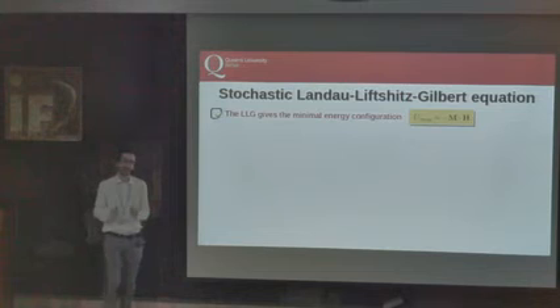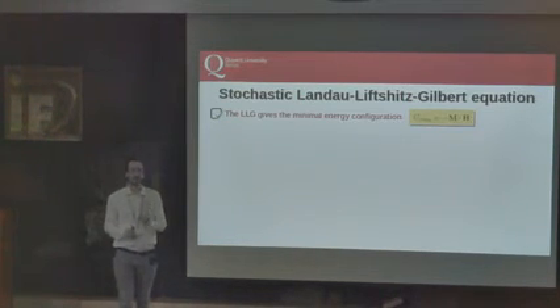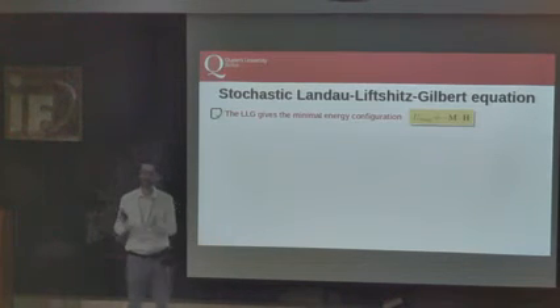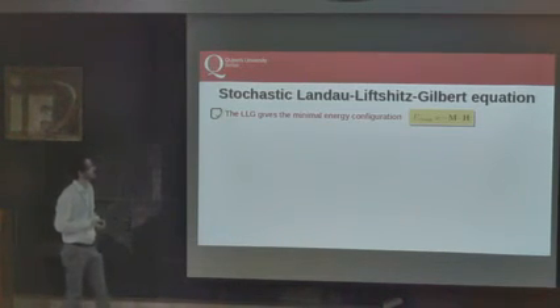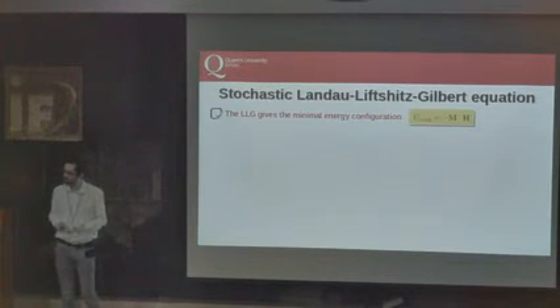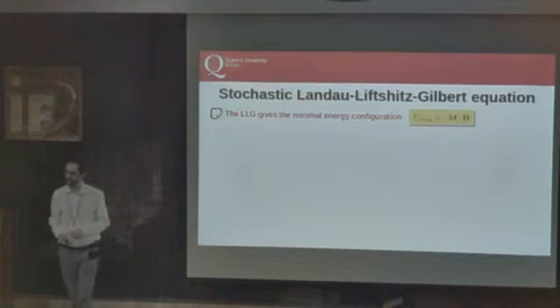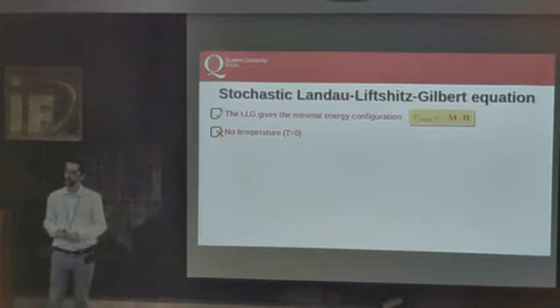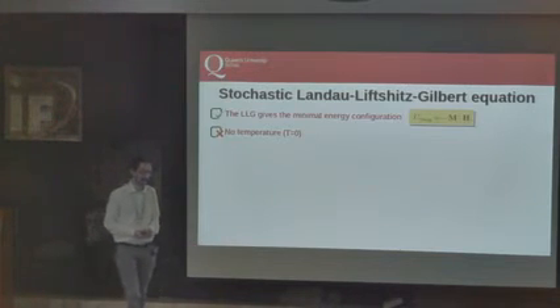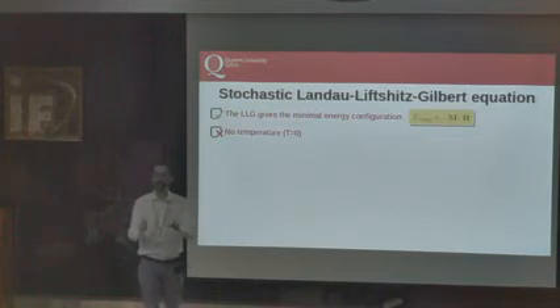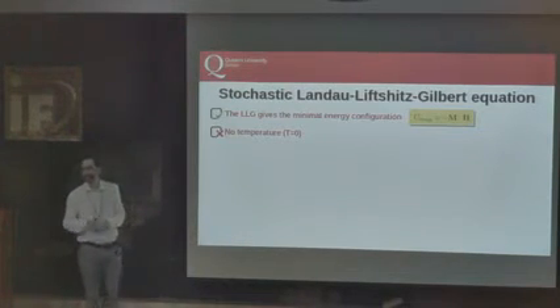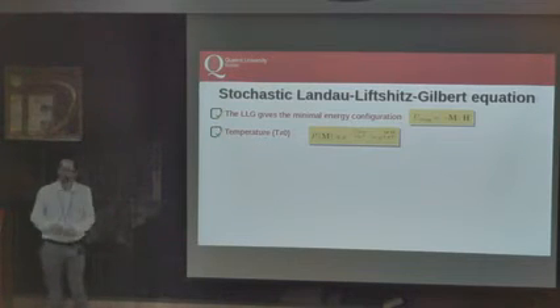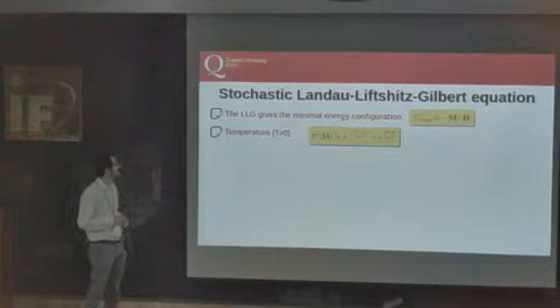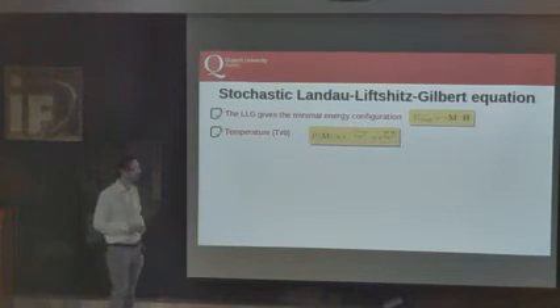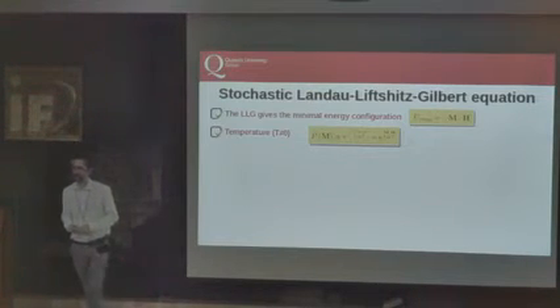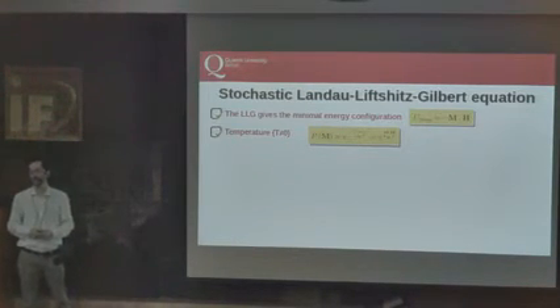If you've been following up to this point, I covered, let me say, the deterministic part of the motion. I still didn't cover the stochastic part. Since I introduce friction, the system will try to minimize the magnetic energy. And you are really sitting at the minimum of the potential energy, magnetic energy, in this case, at 0 temperature. But this is not the range of temperature that we want to target. We want to target room temperature, slightly above room temperature. So we need to introduce also thermal fluctuation. So there will be a distribution of magnetization, not just a value which minimizes the magnetic energy.